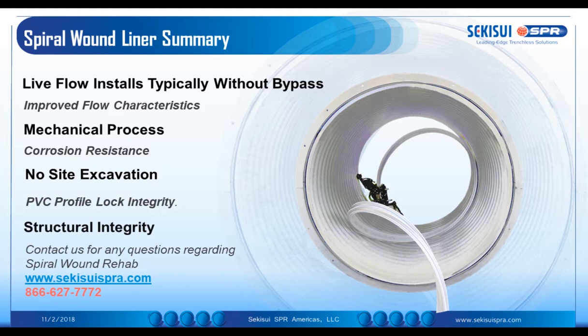We have done the long-term testing according to the ISO standard. Now that's typically out to 50 years, but the data can, with a sufficient degree of correlation, be extended further. I do recall that we have had one design where it required an 80-year design life. And so yes, that can be readily done. It just requires a further extrapolation of that creep test data.